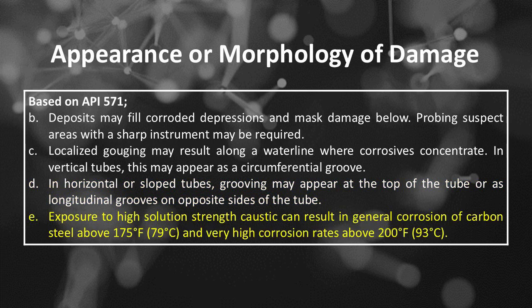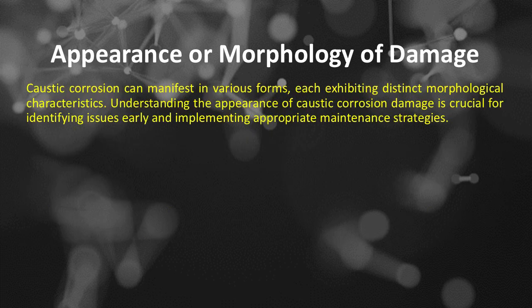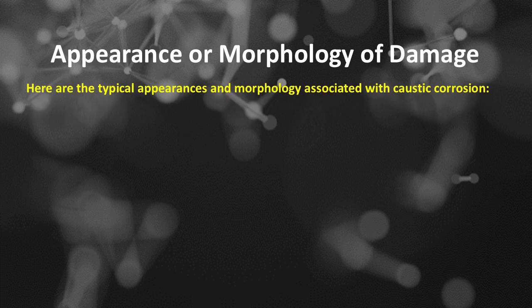Number E, exposure to high solution strength caustic can result in general corrosion of carbon steel above 175 degrees Fahrenheit or 79 degrees Celsius, and very high corrosion rates above 200 degrees Fahrenheit or 93 degrees Celsius. Caustic corrosion can manifest in various forms, each exhibiting distinct morphological characteristics. Understanding the appearance of caustic corrosion damage is crucial for identifying issues early and implementing appropriate maintenance strategies. Here are the typical appearances and morphology associated with caustic corrosion.